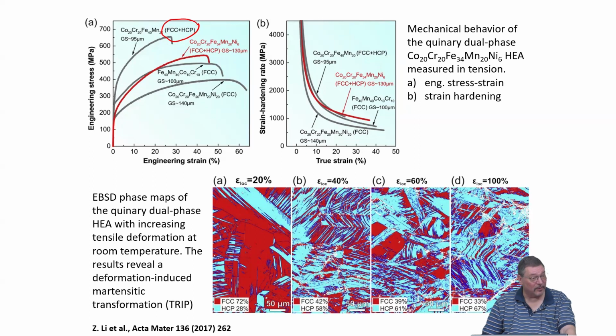It's a stacking fault, right? It's a different stacking sequence. So you go from AB, AB, AB to ABC, ABC, ABC, and that just makes a transformation. They have both the same packing density, and this is why this process can occur so quickly, right? Going from FCC to HCP.